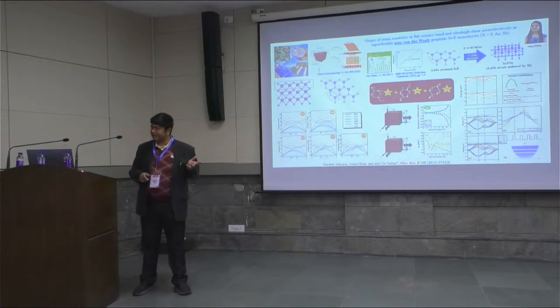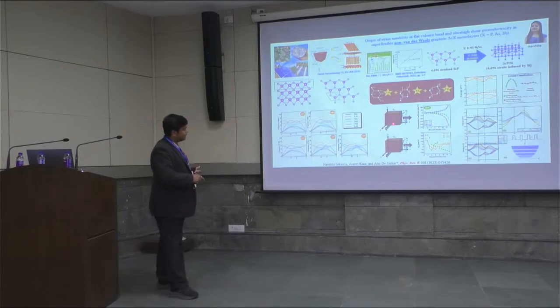So usually this is d16, I think this is not okay, the clarity in the pictures. Okay, d16 is the shear piezoelectric coefficient. These are normally overlooked and ignored in two-dimensional materials, and they are usually studied in helical structures such as DNA nucleobases. And interestingly, these monolayers show a shear piezoelectricity. Shear piezoelectricity is like this. If you apply a torsion, a shear about the z direction, polarization is induced along the x direction.